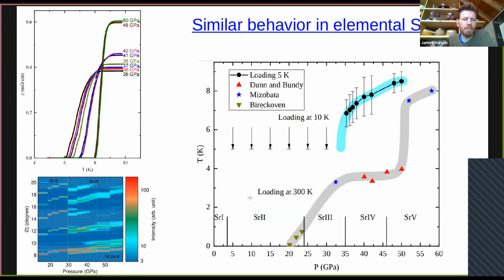And it turns out that what appears to be going on here is that the strontium-3 phase is persisting to higher pressures than previously observed. So basically, what appears to be happening is we've taken this slope for strontium-3, and when it would normally transition to a phase with a lower TC, via cryogenic compression we've kind of continued to push TC higher. So I think these approaches have some interesting possibilities.